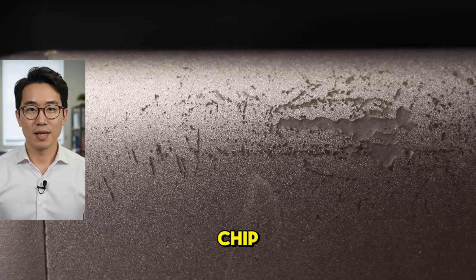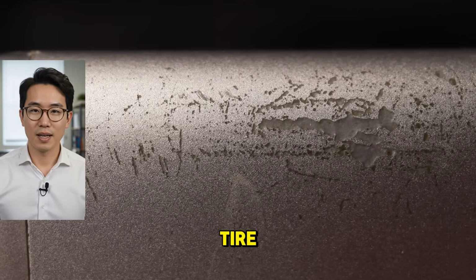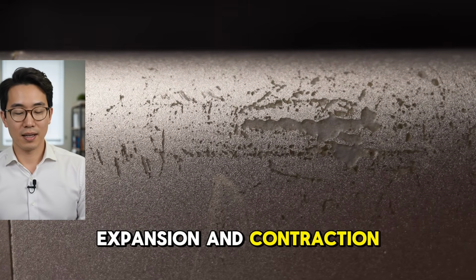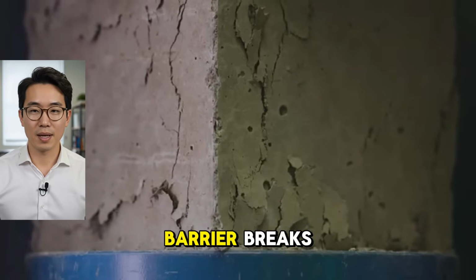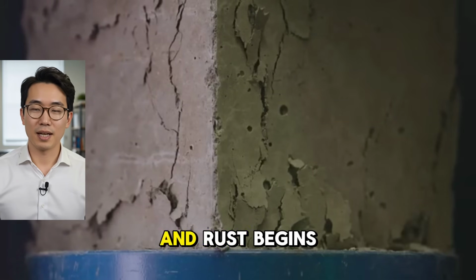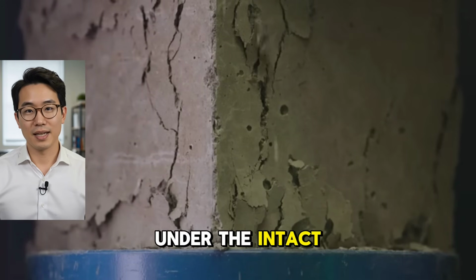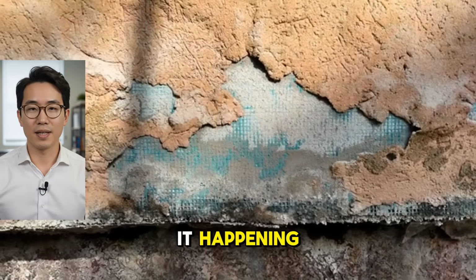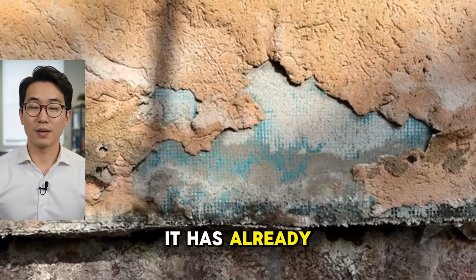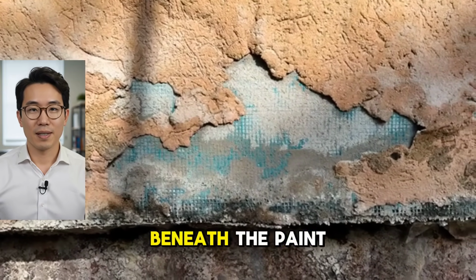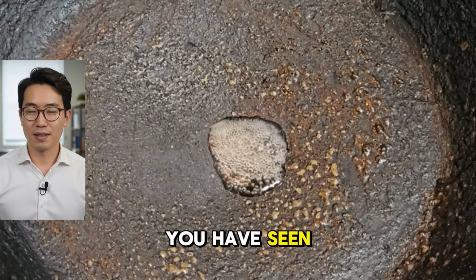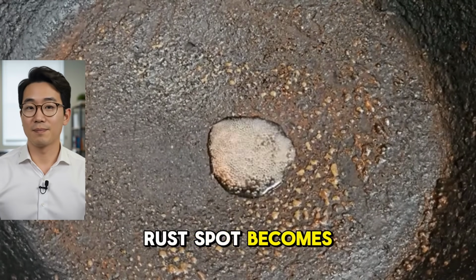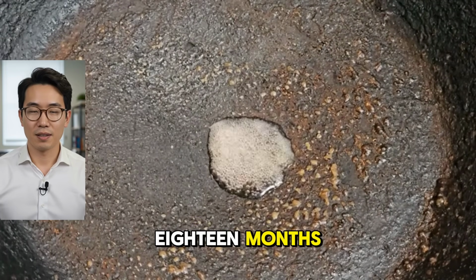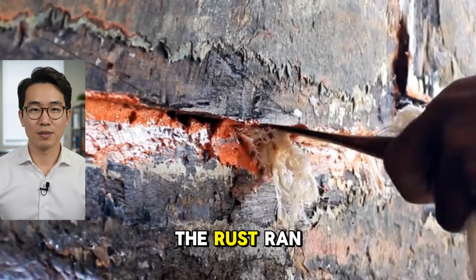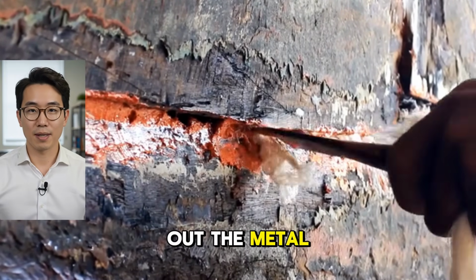A scratch, a chip, a stone kicked up by your tire, a crack from thermal expansion and contraction through seasons. The moment the barrier breaks, moisture gets underneath it, and rust begins spreading laterally under the intact coating. You cannot see it happening. By the time you notice it on the surface, it has already spread 3 inches in every direction beneath the paint. This is why you have seen cars where a small rust spot becomes a hole in 18 months. The barrier failed at one point. The rust ran under the protection and hollowed out the metal from beneath.